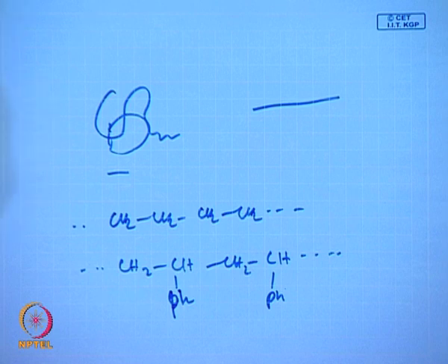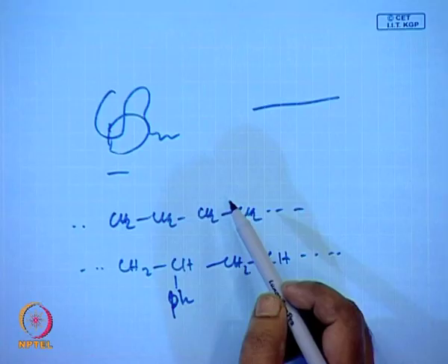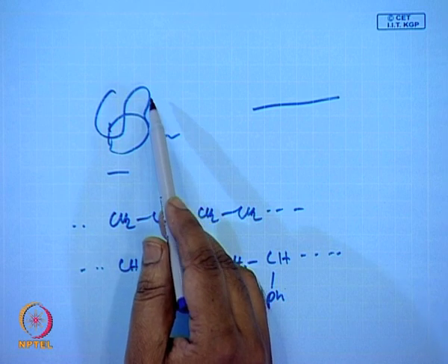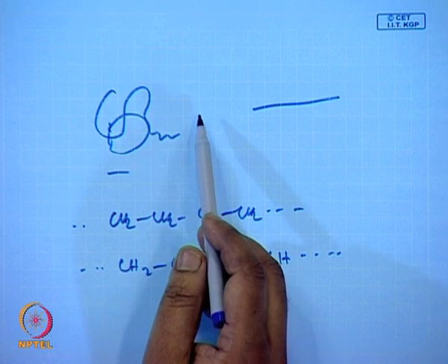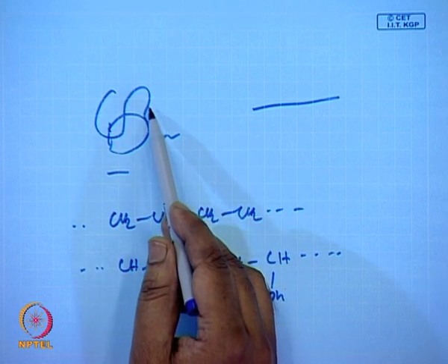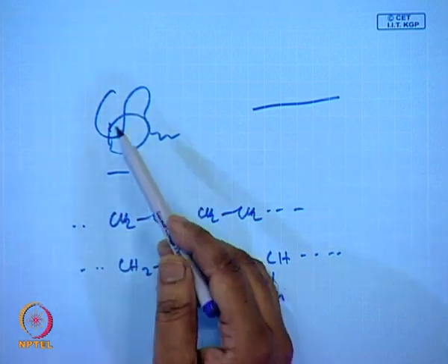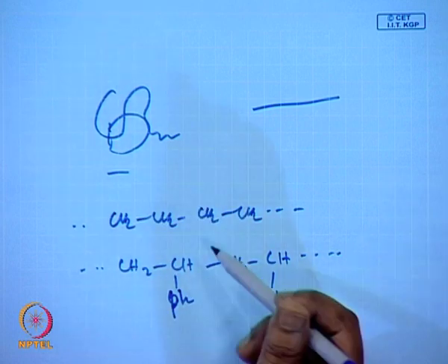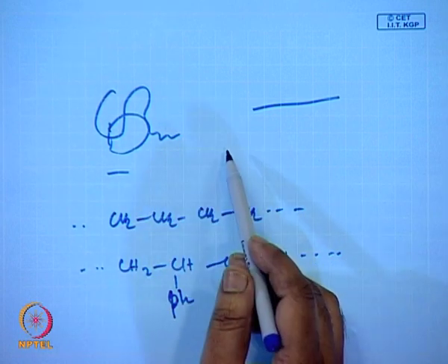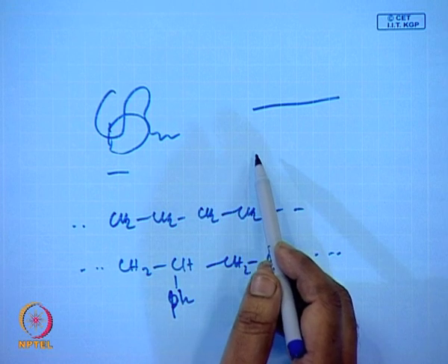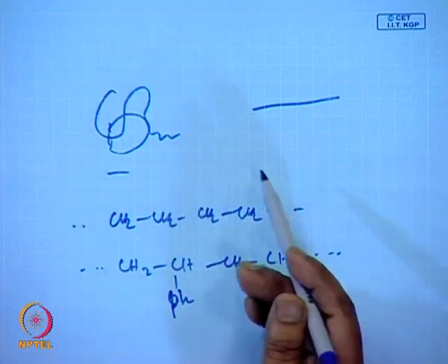The third one is of course the molecular environment, which depends upon where the polymer is. If the polymer is in a solvent, then if the interaction between polymer and solvent is higher than the mean interaction between solvent and polymer, then the polymer-solvent interaction will be preferred. So the polymer will try to expand its chain, to become bigger in size. If the polymer-solvent interaction is lower compared to the mean interaction of polymer and solvent, then it will try to contract and avoid the solvent